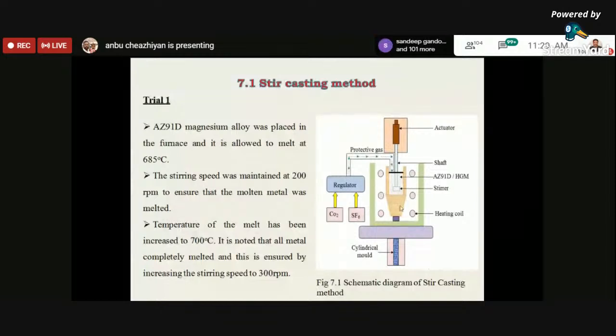Here we have placed the AZ91 magnesium alloy, and it is melted. The reinforcement is called nanospheres or hollow glass microspheres. The glass spheres seem to be hollow sometimes, so we go for hollow glass particles, nano glass particles. The metal is melted in a resistance heating furnace, and the stirring speed was maintained at 200 rpm to ensure the metal was melted.